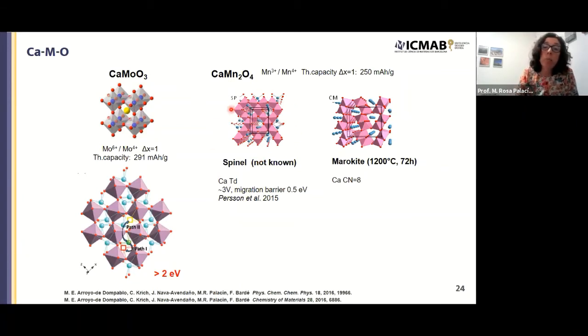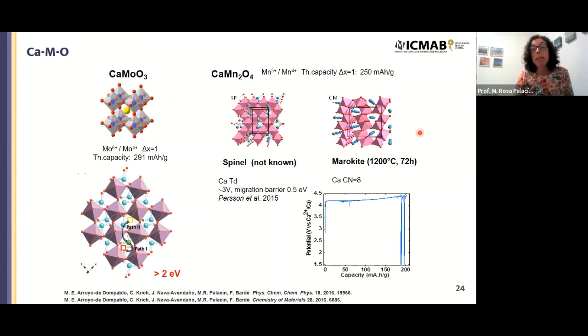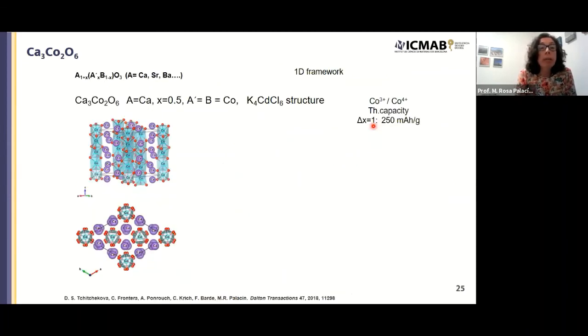In fact, nobody has been able to prepare this polymorph, and the stable polymorph is the marokite one, which is this one, which we were able to prepare, that has some channels in the crystal structure along which maybe calcium could move. This is the electrochemical attempt to oxidize this compound. We see this plateau at high potential, which, coming from the lithium-ion battery field, one could think, oh, maybe this is the oxidation and it is irreversible. But in fact, when doing X-ray diffraction, we realized that nothing changed, and this is simply electrolyte decomposition. Again, we understand this because when we calculate the migration barriers, they are very high for this crystal structure. So then we became interested in